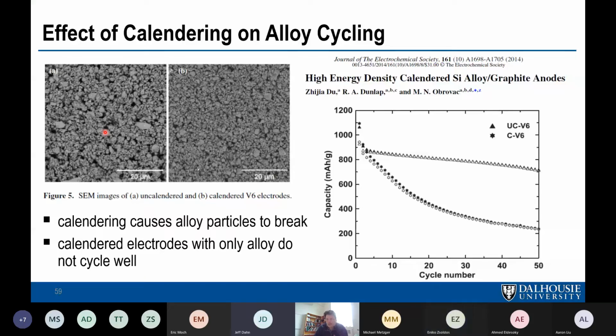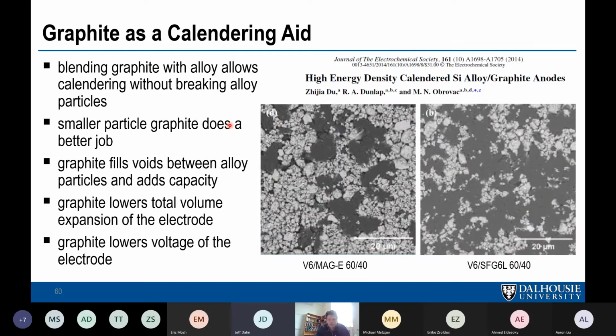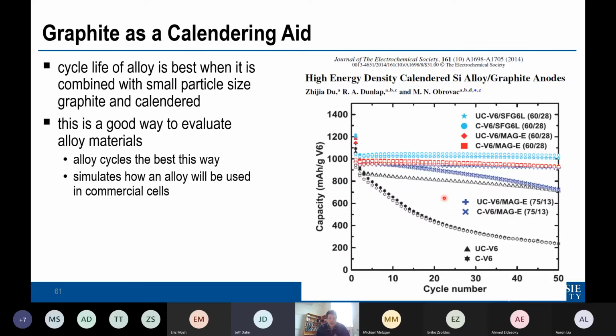I guess it's kind of like trying to make a brick wall where the bricks are nicely stacked by throwing the bricks into a pile. You're never going to do it, no matter what the particle or size distribution of the bricks is. They're never going to come together and form this kind of interlocking pattern. You can see how nicely the particles fit together when they're calendered. You can't do that without pressure. And if you add graphite, the particles don't break anymore, and you see that in the cycling.